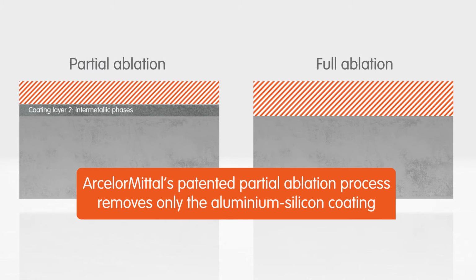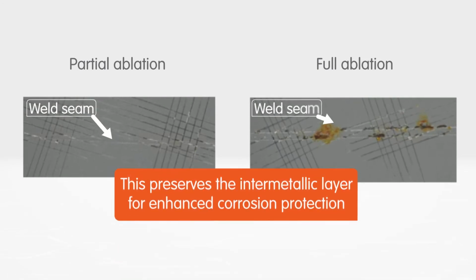ArcelorMittal's ablation process partially removes the aluminium silicon coating near the edge of the part. This prevents excessive aluminium in the weld. However, the intermetallic layer is preserved, guaranteeing corrosion protection.